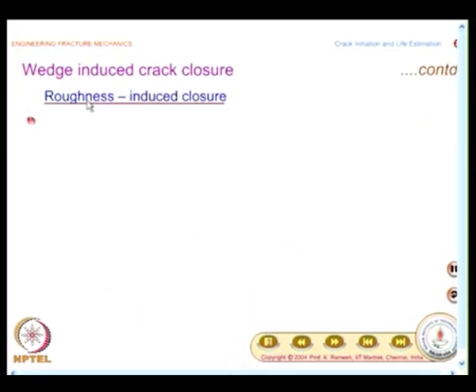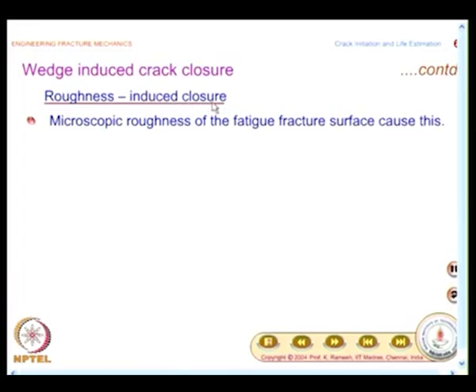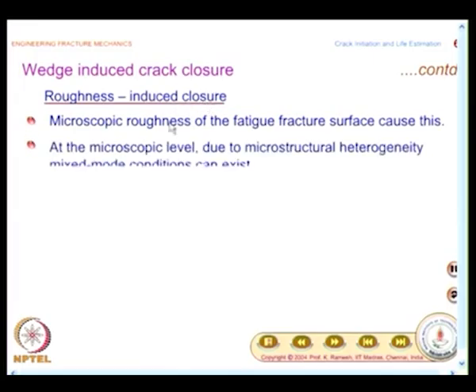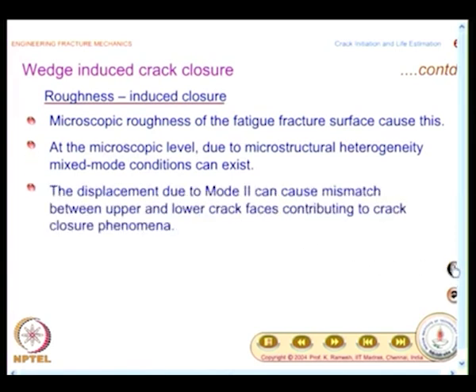Then you also have roughness induced closure, this is another phenomenon, and what is reported is that microscopic roughness of the fatigue fracture surface caused this. At the microscopic level, due to microstructural heterogeneity, mixed mode conditions can exist. Once you come to here, too much material science knowledge you need to have, it is all highly exaggerated pictures I am going to show.